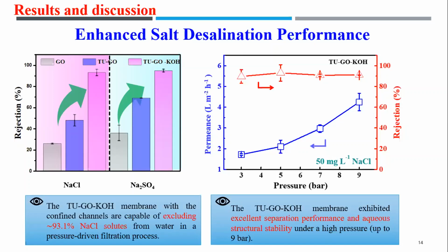On the other hand, the TU-GO-KOH membrane still has excellent separation performance under high pressure up to 9 bars, indicating that the membrane possesses a robust microstructure and could withstand a high pressure up to 9 bars. Thus, mechanical stability is also crucial for industrial application.